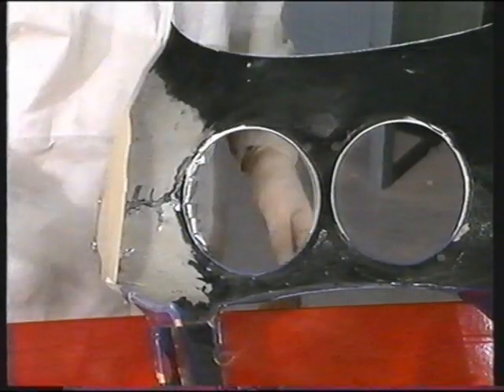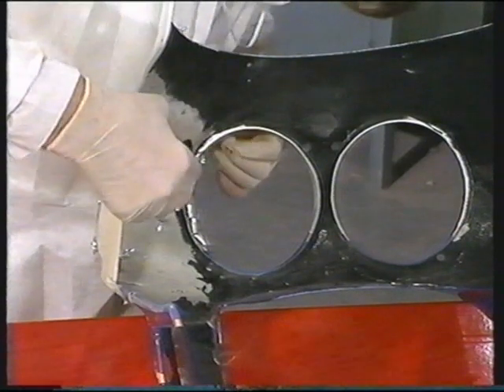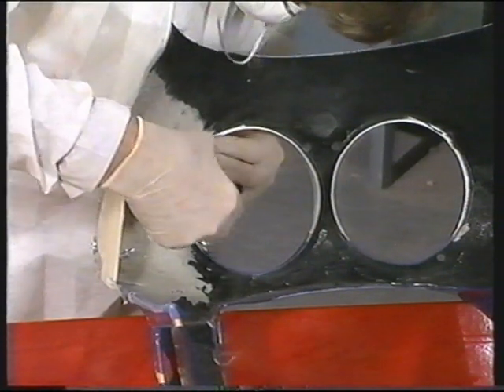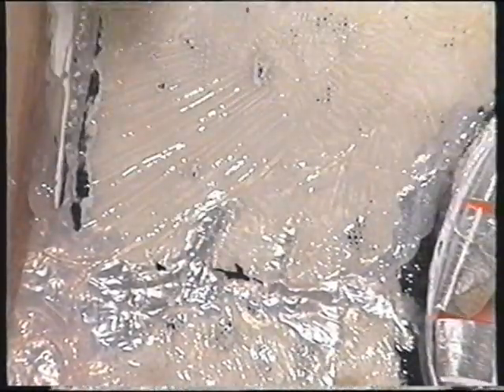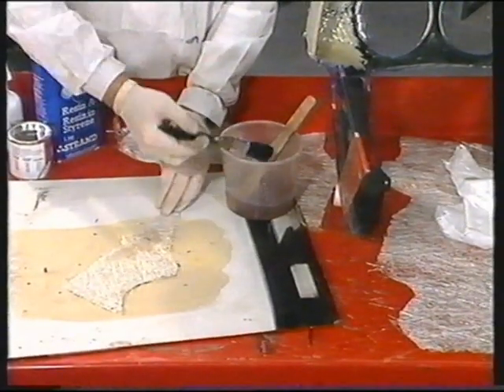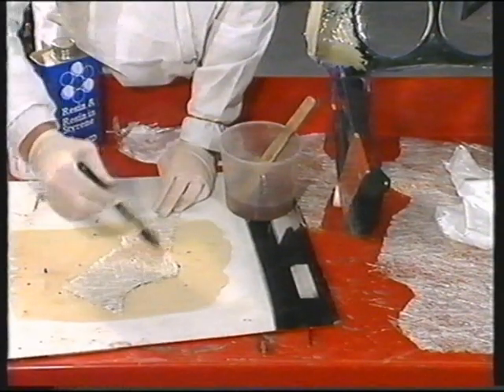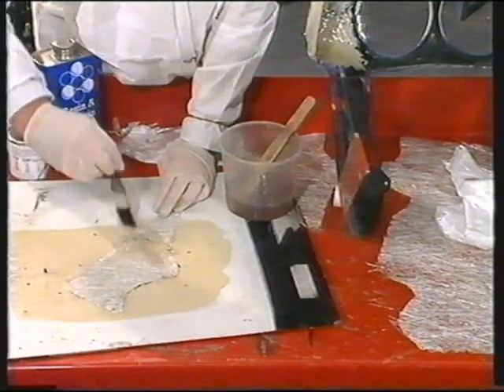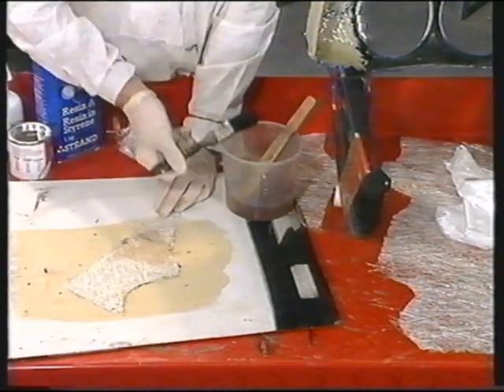The gel coat has been weighed out accurately and is now being mixed with the hardener in the ratio recommended by the manufacturer. This is applied to the damaged area, sealing it and providing a sound base for further work. This is left to cure for about an hour until tacky. Meanwhile, the resin has been weighed out and mixed. It's applied to the chopped strand glass fibre matting using a stippling action to remove air bubbles.